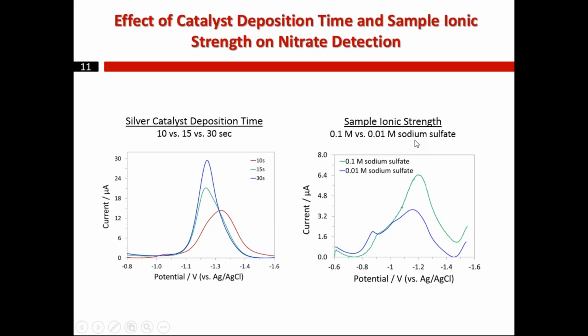Another factor that has to be considered was the effect of ionic strength. So you can think that when you're collecting water samples in the real world, they might have different amounts of salt dissolved in them. Therefore, the ionic strength of the samples might be different. Therefore, we had to make sure that the sensor that we have developed is sensitive toward nitrate in a variety of ionic strengths. And as you can see over here, we observe that this sensor can be used for detection of concentration of nitrate in both high and low ionic strengths.